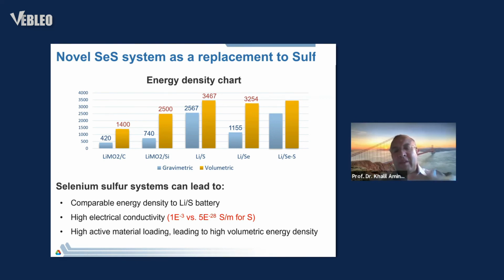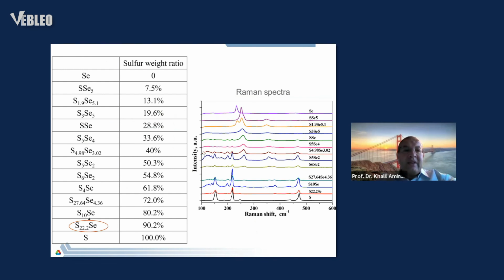If you look at the phase diagram, there is a whole bunch of phases. Once you start adding selenium, the conductivity of the material goes up. So we thought maybe that's the best approach to address the conductivity. These are the phase diagrams. Of course, selenium is expensive, about $80 a kilogram. You can buy a ton of sulfur with that. But if you use the lowest amount of selenium, like S22.2Se, then the cost goes double, basically, from 110 to 220 a ton, which is extremely low cost.